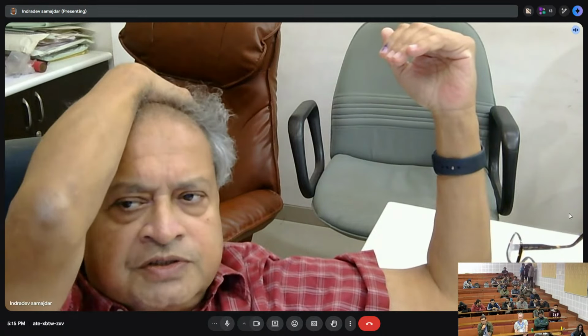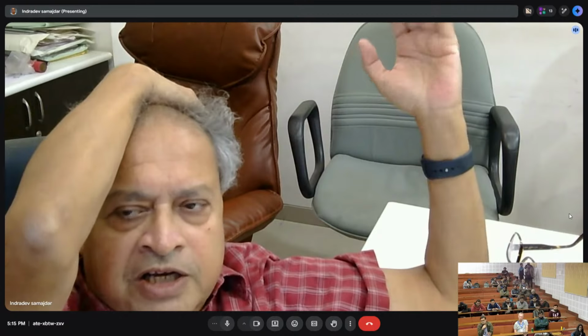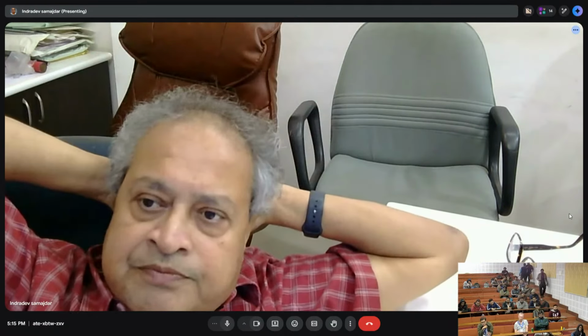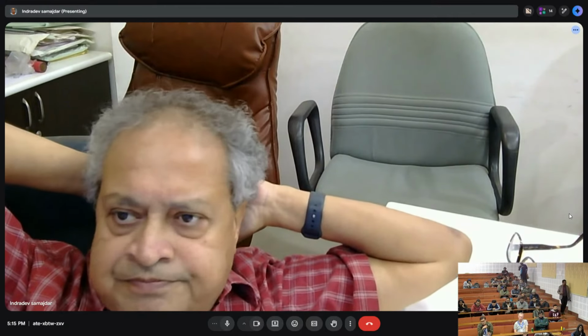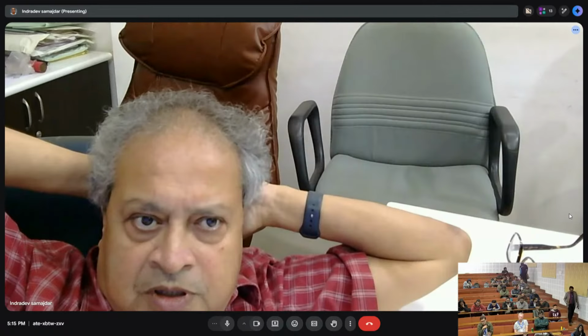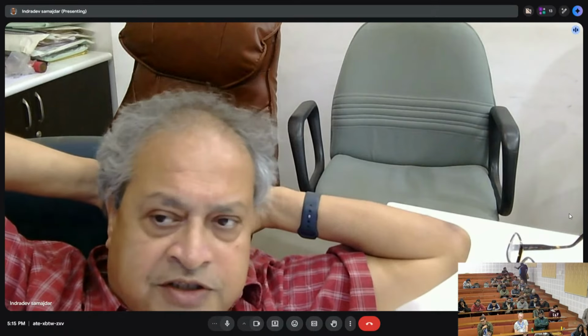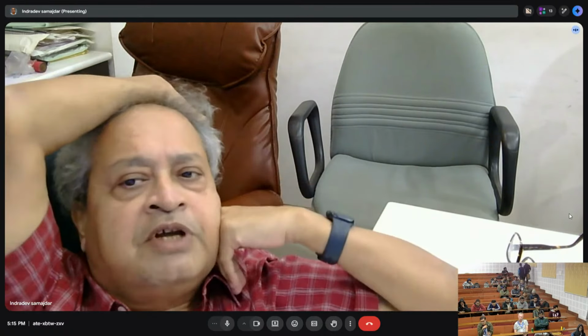Of course it does. But in addition to that, there can be errors in the measurement. For example, if your lambda is not very fixed, you are going to have plus minus delta lambda. That's a disaster. That is the reason, first of all, people like synchrotron other than the beam intensity. These are intrinsically lower delta lambda.